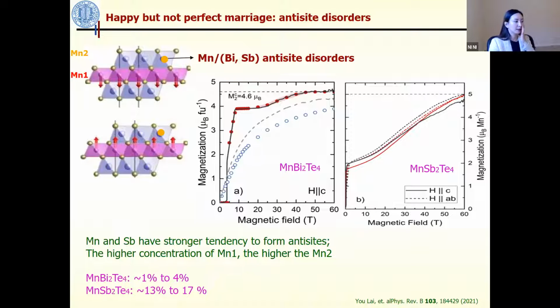Why is that? For material design, or in theory calculation, you always think, oh, manganese should be at the manganese site, bismuth should be at the bismuth site. But in reality, when we grow samples, there could be deficiencies, there could be antisite disorders. It turns out for this family of compounds, a recent publication from Oak Ridge National Lab showed, based on high magnetic field measurements, that the manganese bismuth 2 tellurium 4 compound has 1% to 4% of antisite disorder. And the manganese antimony 2 tellurium 4 has 13 to 17% of antimony to manganese antisite disorder.